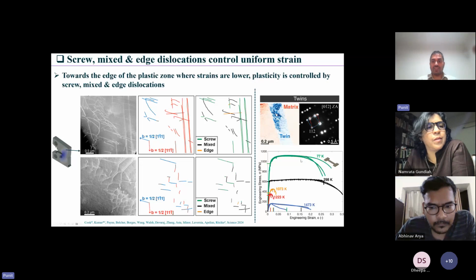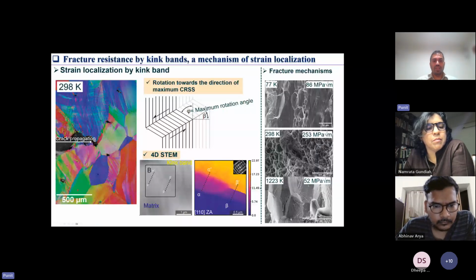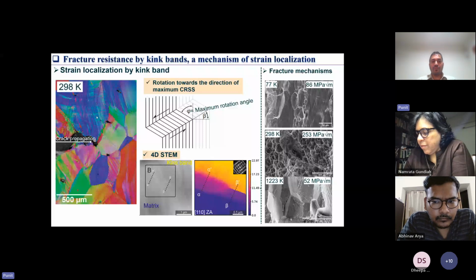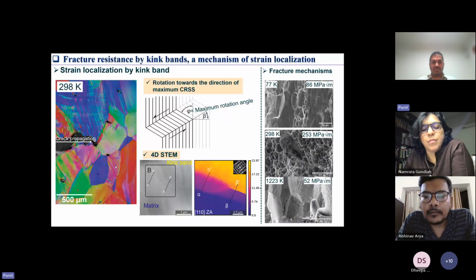But in the case of fracture, when you have a crack tip, the mechanism becomes really interesting, because now you can nucleate more and more kink bands, like this amount of kink bands. Usually kink bands have been investigated in single crystals and nanowires, where you see some kink bands forming, and that's where strain localizes. But in this case, you can nucleate a lot of kink bands in the same grain, and kink bands also interact with each other, like a kink band ending on another kink band. And that is happening because it's related to the atomic level mixing of the elements that we have in this case.